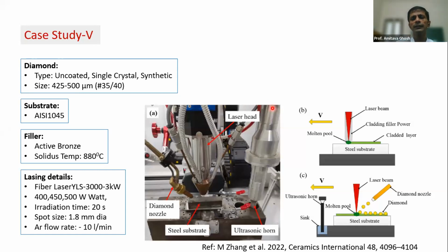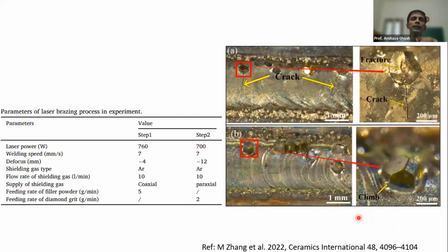Okay, so this was another attempt where the group wanted to introduce the diamond through a nozzle, from a side direction, so that the laser will not interact with it for a long time, within that small millisecond time span I'm talking about. In all these attempts, they're reporting the pulse width is just a millisecond, whenever they are using a pulse. Otherwise the scan speed should be such that the irradiation time on a particular grit is well controlled. It may not be in milliseconds in that case, but on the order of 10-20 seconds.